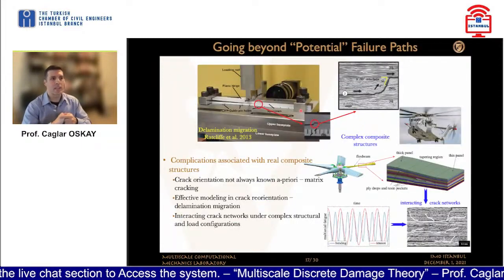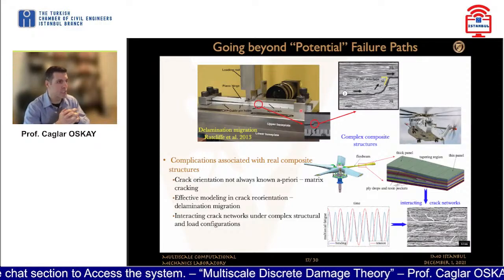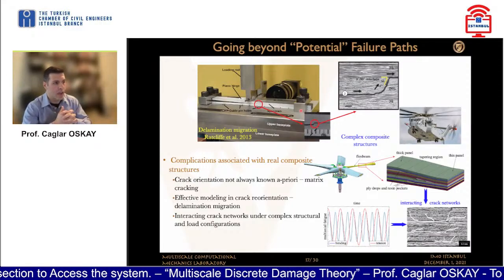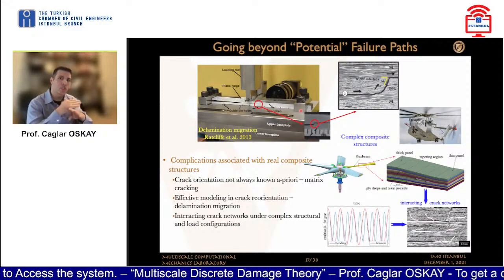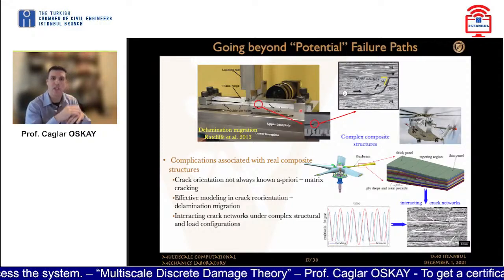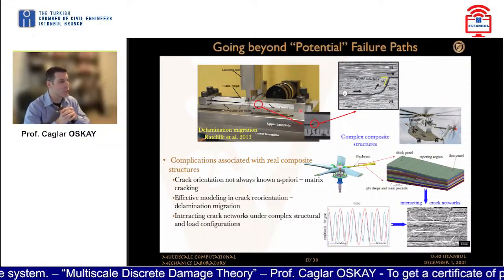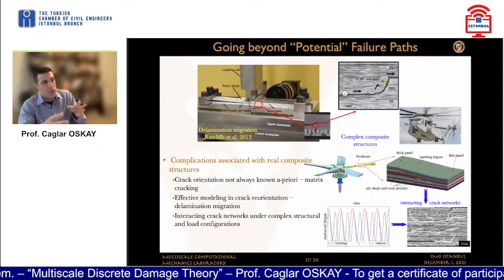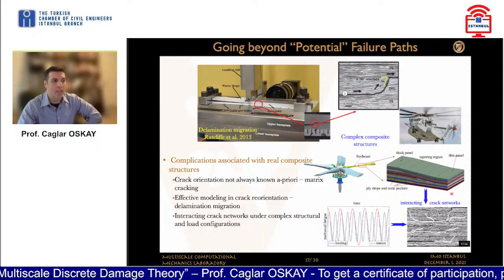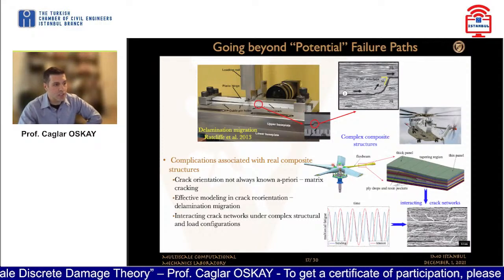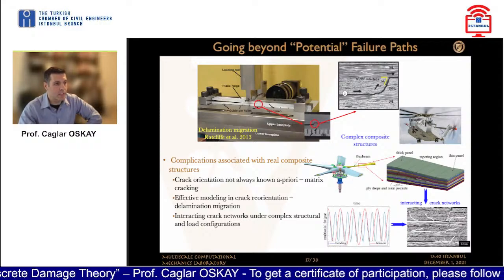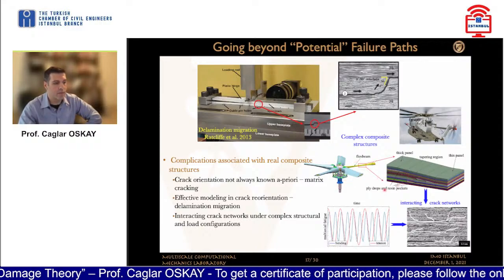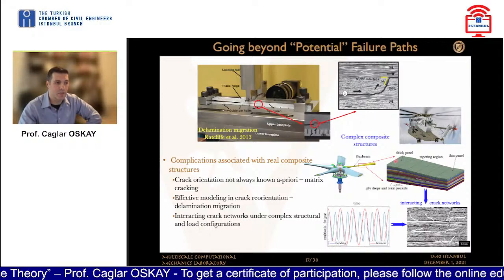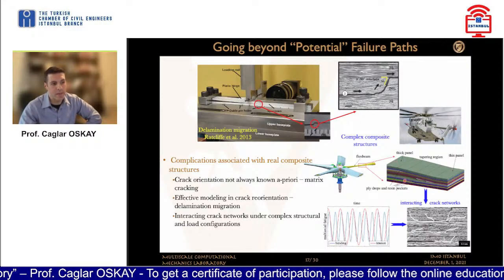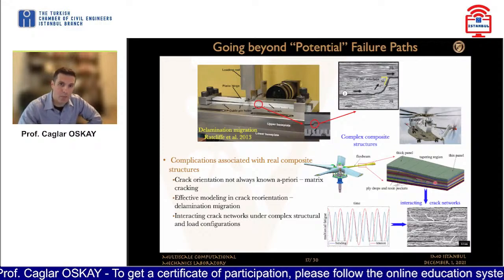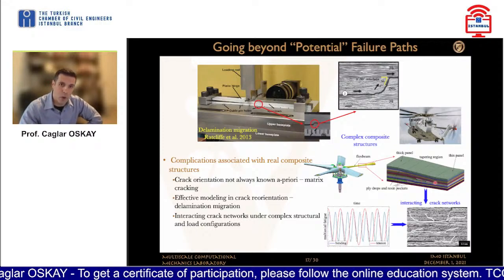Let's go beyond the potential failure paths idea. So this is the second part of the presentation. One of the things that we have assumed is the orientation. We know the orientations of these potential failure paths. In general, once you start going into slightly more complex composite structures, such as this rotor assembly right here, where you have a ply drop in the system that goes from a thick panel to a thin panel, there are necessarily going to be additional complications, and the behavior is going to be quite a bit more complicated.